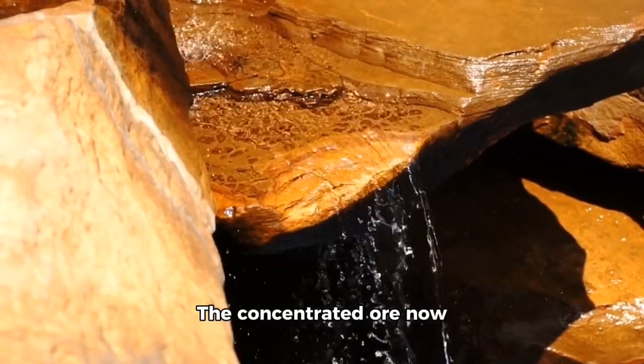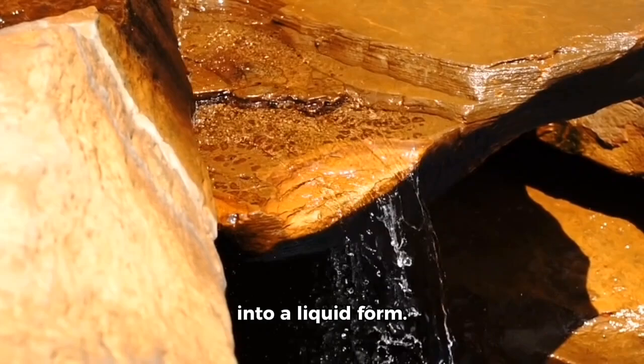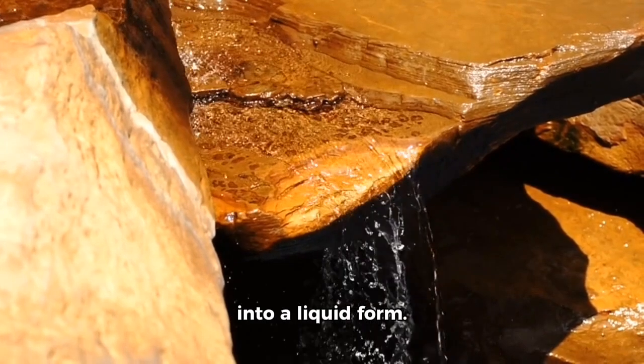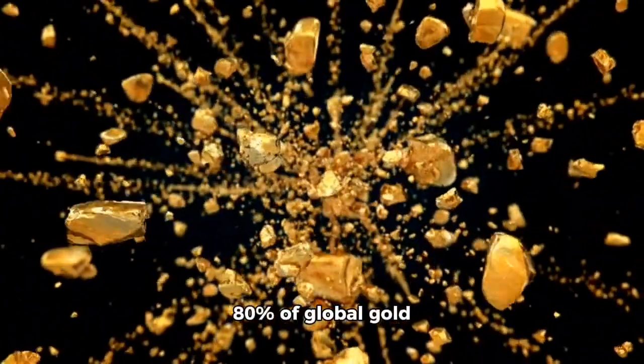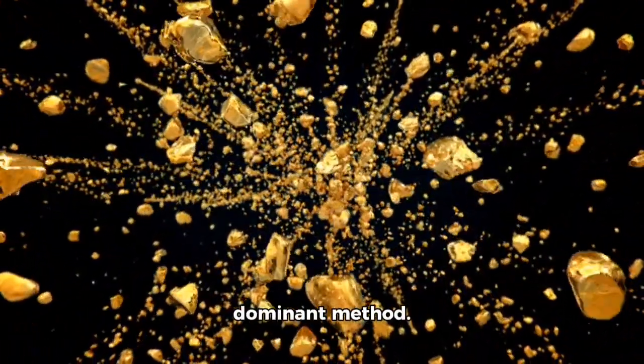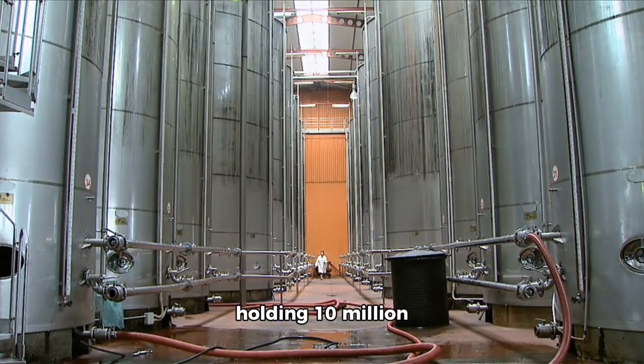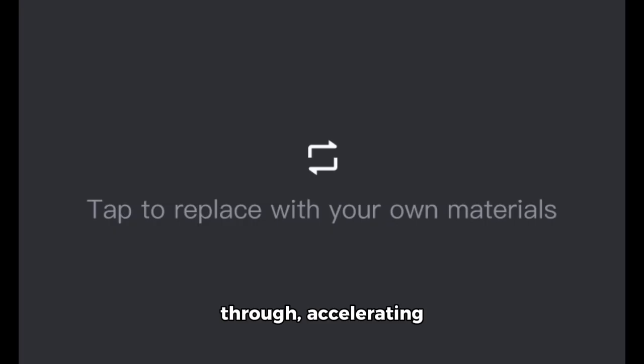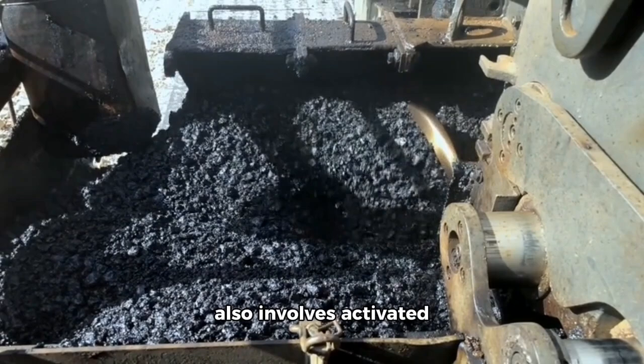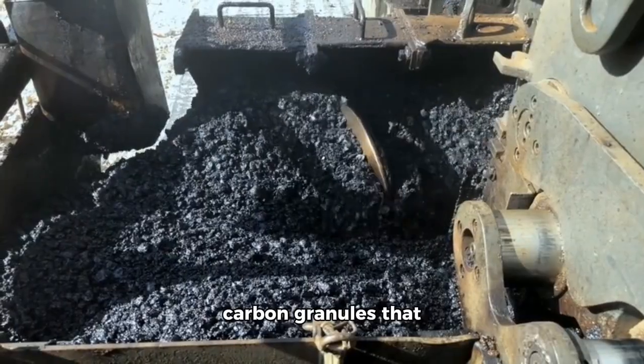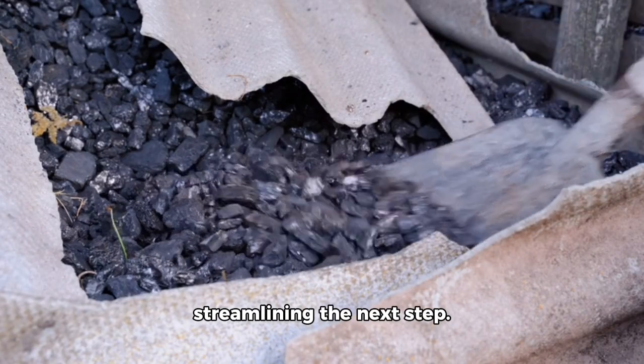The concentrated ore now enters the leaching and extraction phase, where chemistry dissolves gold into a liquid form. Cyanidation, used by 80% of global gold production, is the dominant method. In massive tanks, some holding 10 million liters, the concentrate is mixed with a dilute sodium cyanide solution, 0.05% concentration. Oxygen is bubbled through, accelerating the reaction as cyanide binds to gold, forming a soluble complex. The process, known as carbon-in-leach, also involves activated carbon granules that absorb the dissolved gold, streamlining the next step.